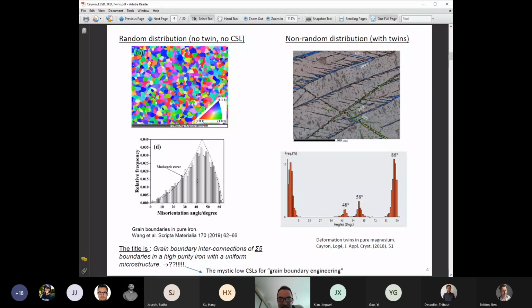On the contrary, if you look at the right side of the slide, it's a magnesium alloy, a single crystal, in which I could form twins during cutting. Actually, when I cut the sample, I form the twins. And if you look at the histogram of misorientation between the grains, here it's very clear. You see peaks at 48, peaks at 58 degrees, and one peak at 86. So it's completely non-random. You form specific misorientations, and that's what we call twins.